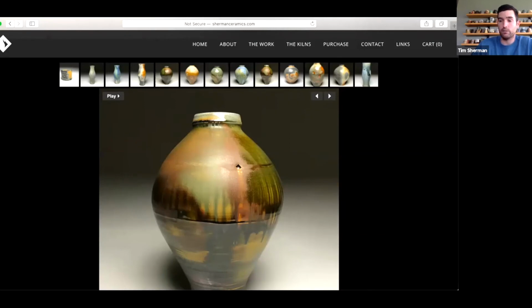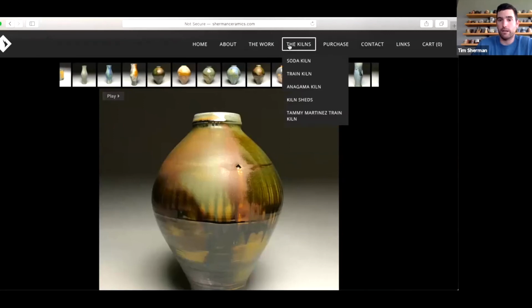And then vice versa, if you have very little air and the passives are wide open, what you'll notice is if your kiln has a blowhole, there will be tons of smoke and fire coming out of that blowhole. That's probably too slow. So I try to gauge the pressure and the speed of the flame by those holes in the top of the kiln, those blowholes that kind of tell you what's going on without actually looking into the kiln. I don't want to do that if I don't have to. I don't know if that answered your question at all, but that's what I think about when I'm firing.